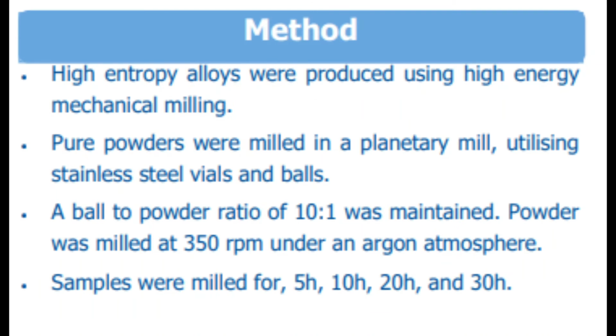The high entropy alloys were produced through high energy mechanical milling. This involves having powders and small ball bearings in a vial that is then rotated at high speeds in a planetary mill. The powders will collide with the ball bearings, which will break them apart and force them to combine and react with other powders so that coherent alloys could be formed of small particle sizes.